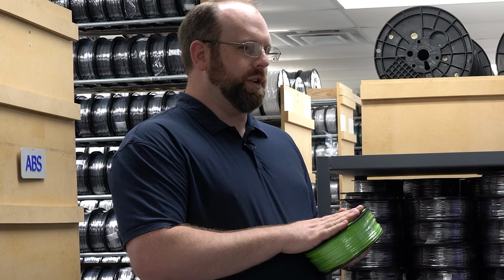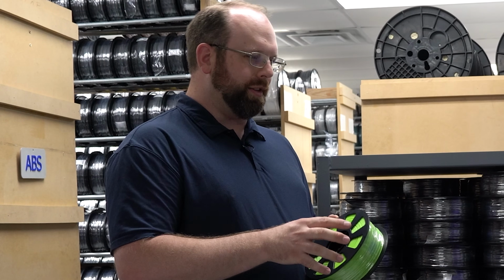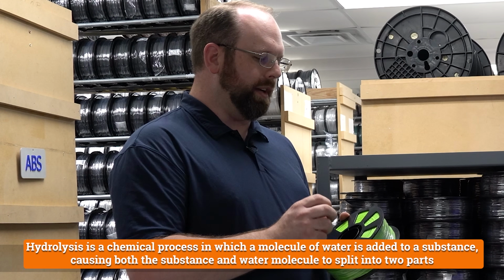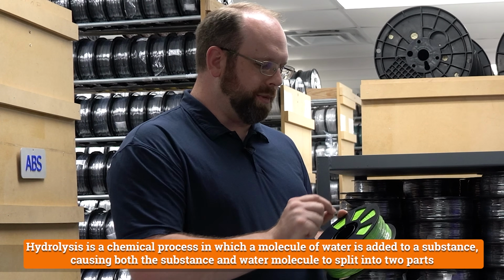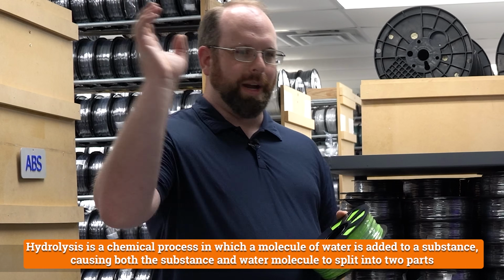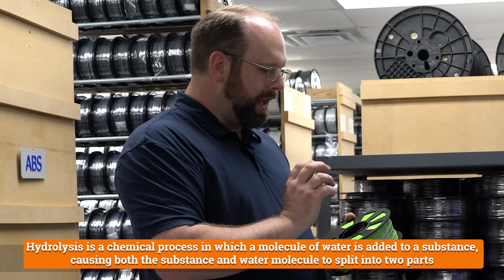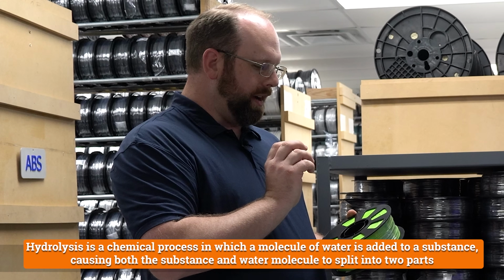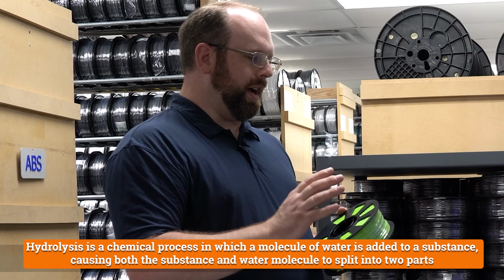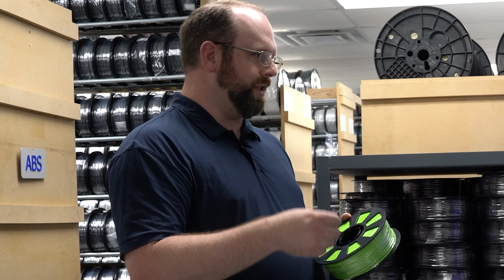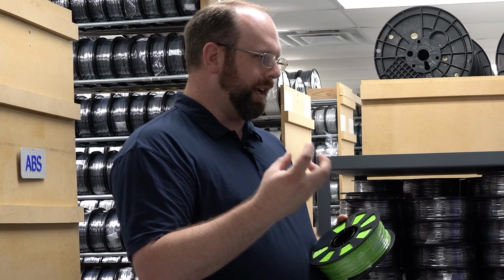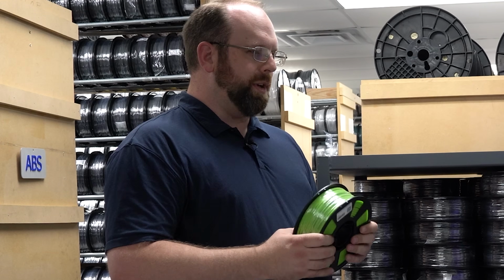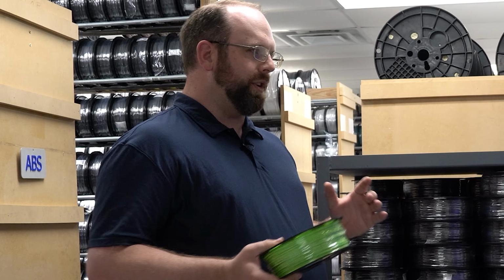But if it were moisture, if it were what they call hydrolysis, which is where the moisture comes in and actually breaks apart the polymer chains, and I described that a little bit with the dryers on the tour, that is permanent. You have to add a polymerizing agent to rebuild those molecular bonds. It actually destroys the polymer chains. Okay. Hydrolysis is really bad. And a filament dryer is not going to reverse that.